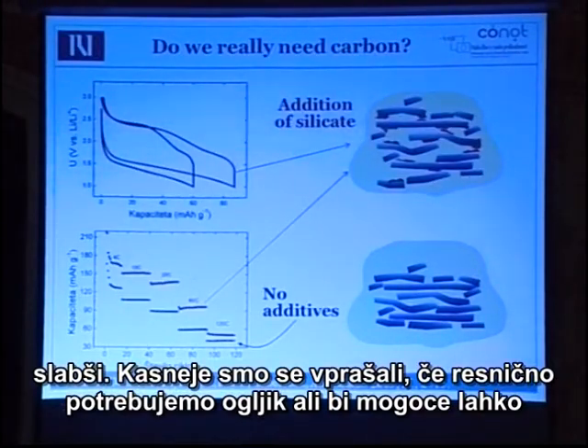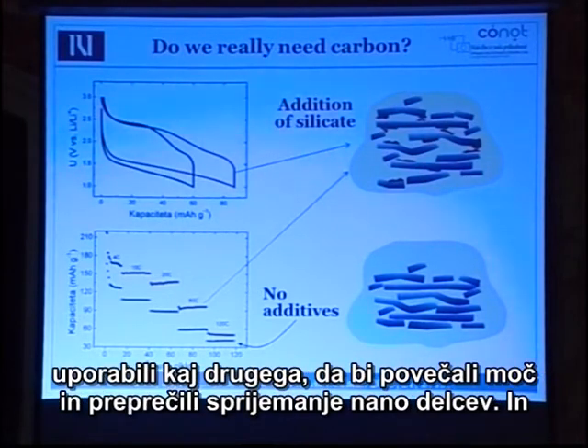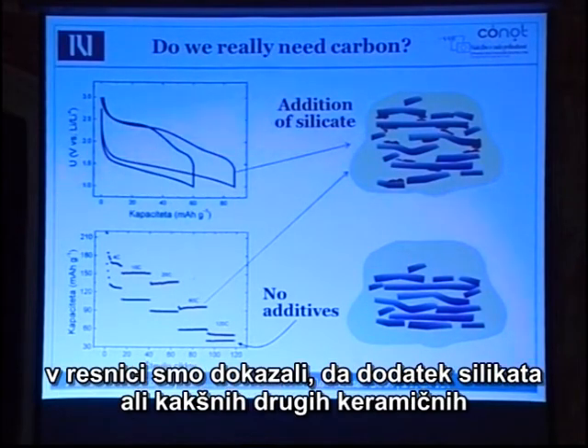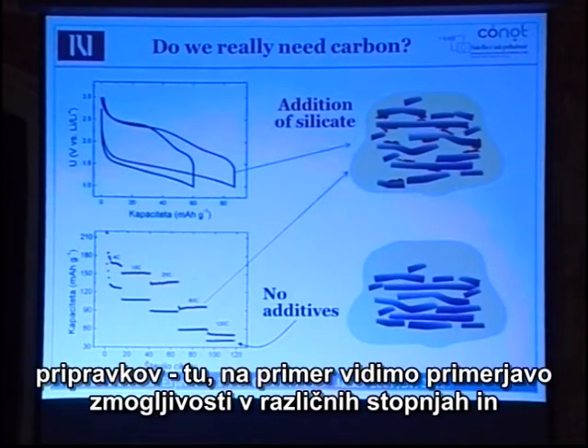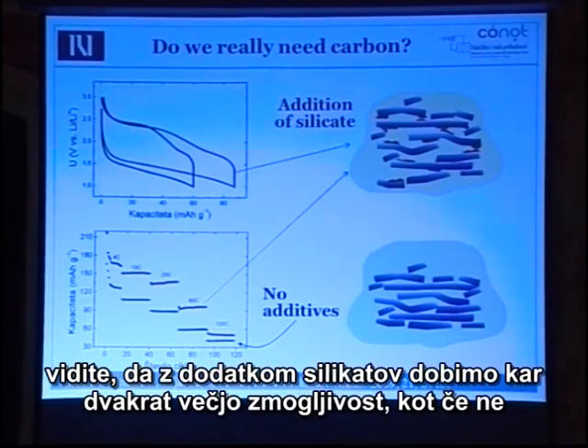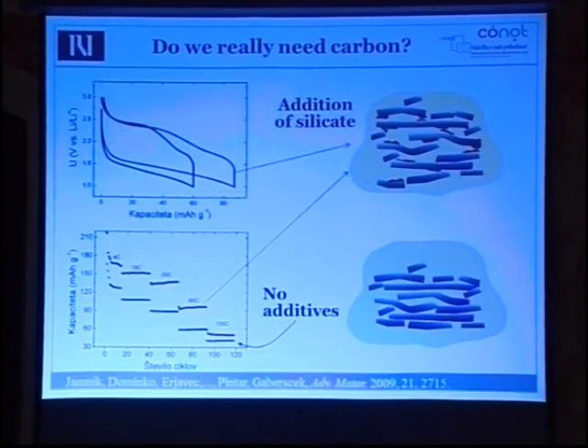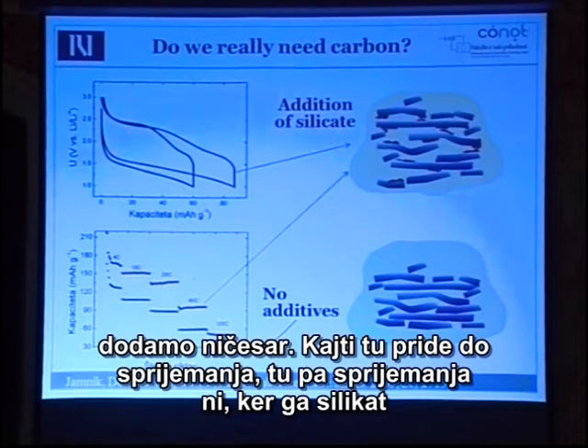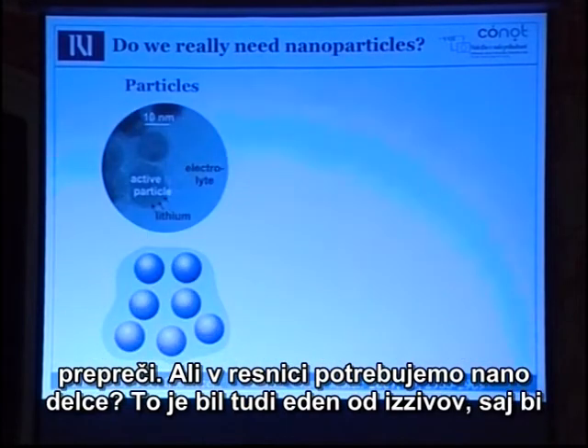Later on, we said, okay, do we really need carbon? Can we use something else to increase the power to separate our particles? We showed that addition of silicate or some other ceramic precursors also helps. So, for example, here we have capacity at different rates, and you see that when you have this addition of silicates, you have much higher capacities, maybe 2 times higher. It's right here. And then if you don't have anything, because here you have agglomeration, here you don't have agglomeration, because this silicate prevents agglomeration.